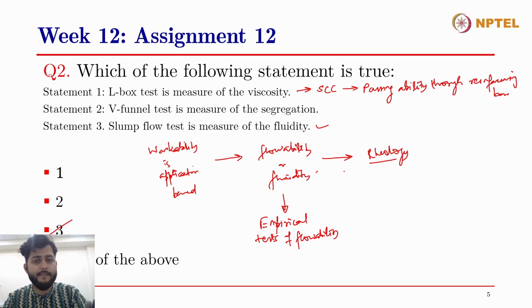The second statement was V funnel test is a measure of segregation. Now, I would say this is neither a right statement nor a wrong statement. In the case of the V funnel test, what you're doing is allowing the concrete to flow under the effect of gravity, right? If a concrete is undergoing heavy segregation in the mix, then the heavier particles, meaning the aggregates, will settle down at the bottom, while the paste and the pore water will rise to the top. And therefore, when this segregation occurs inside the V funnel and you release the bottom opening and let the concrete flow out, it could so happen that due to segregation, the concrete takes a longer time to flow out. So V funnel test sometimes gives us an indication of segregation,